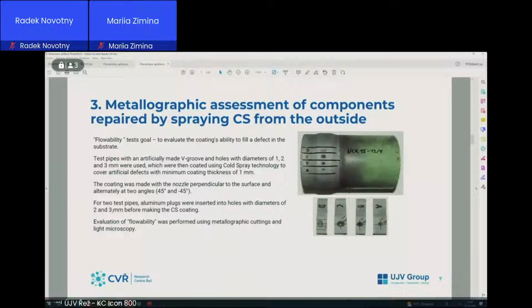We also performed two types of coating. We had a nozzle perpendicular to the surface, and then the second type of coating was alternately at two angles, plus 45 and minus 45 degrees. For one test pipe, we put aluminum plugs into holes with diameters of 2 and 3 millimeters before making cold spray coating. And then we performed metallographical cuttings and light microscopy. Results are here.